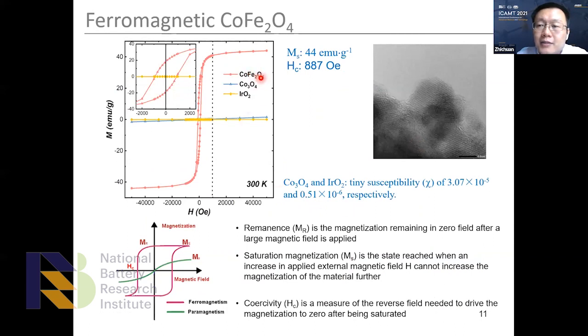Basically, we employed three electrodes: spinel cobalt iron oxide, cobalt oxide, and iridium oxide. The cobalt iron oxide is a ferromagnetic material, and this is its hysteresis loop. We can see the magnetization is roughly 44 emu per gram, and the coercivity is 887 Oe. Cobalt oxide and iridium oxide have pretty much no magnetization, because at room temperature all of them are superparamagnetic or paramagnetic, with very limited response to the external magnetic field.